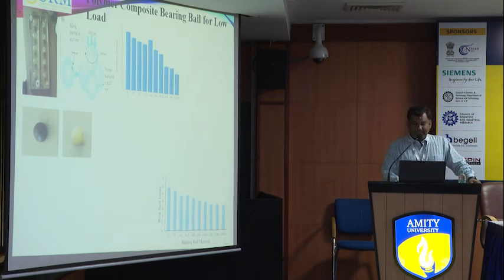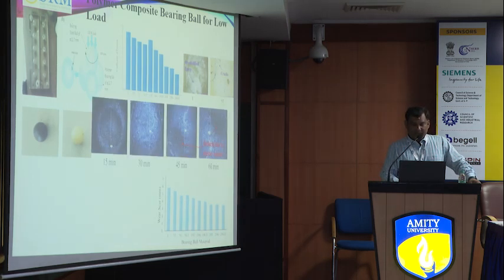For the coefficient of friction, we can see here graphite talc still gives the lowest coefficient of friction. Here no lubricant we are adding, we are only adding the graphite and talc. Pure epoxy, you can see immediately it will fail, and sometimes due to the heat it re-solidifies at the interface. These are the observations we made. But in the case of the graphite and talc ball, we did not observe that much scar. Only plastic deformation occurs that changes the shape, but it does not wear out.